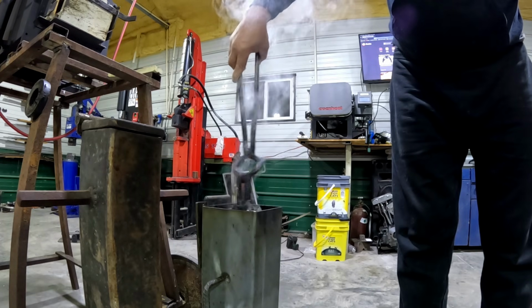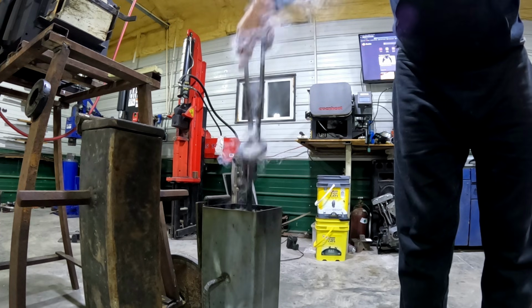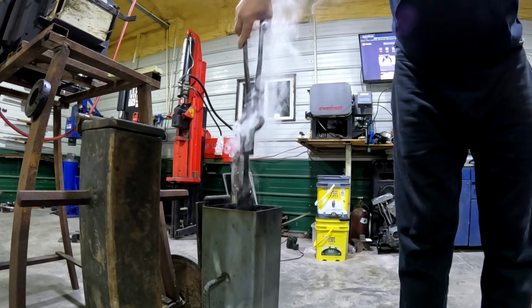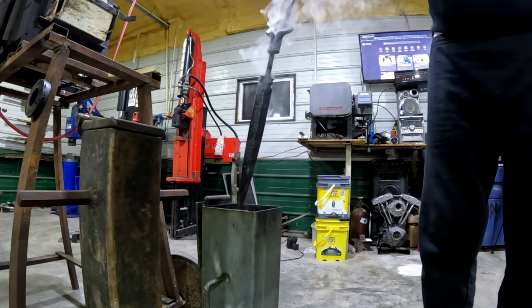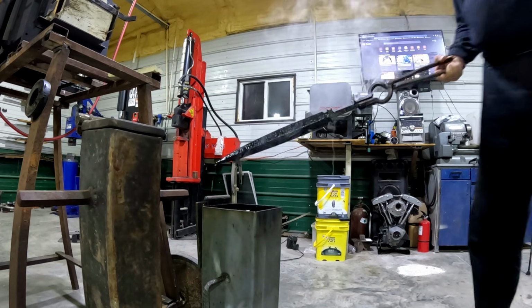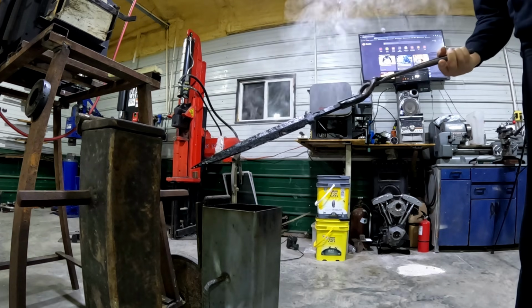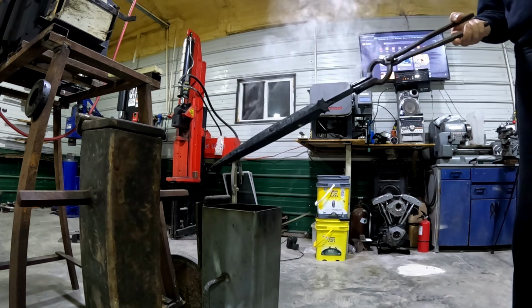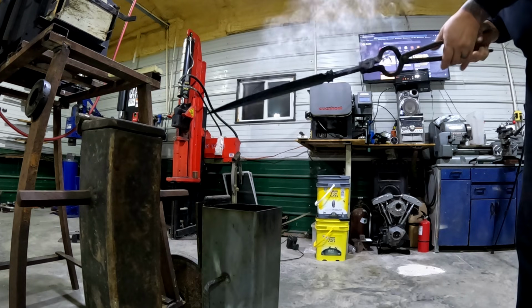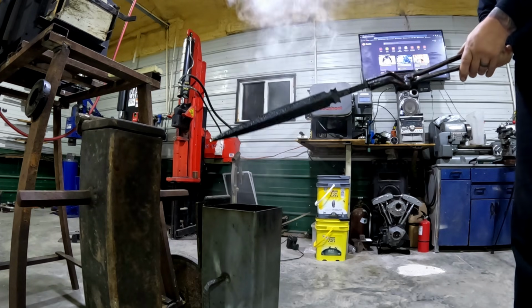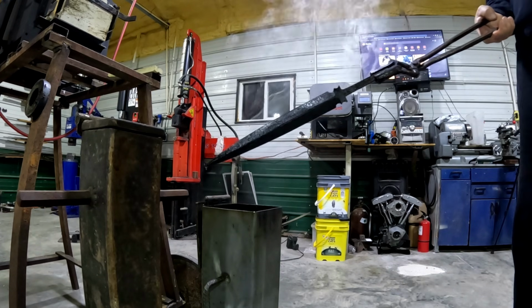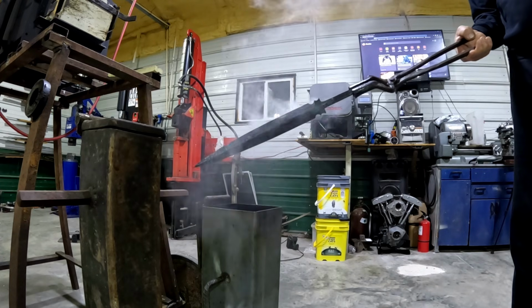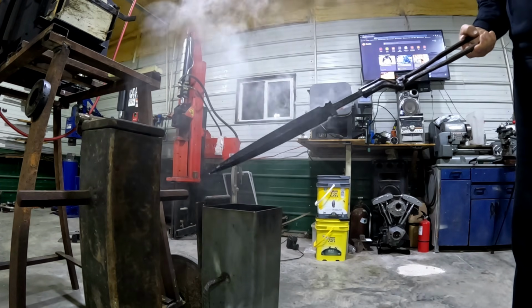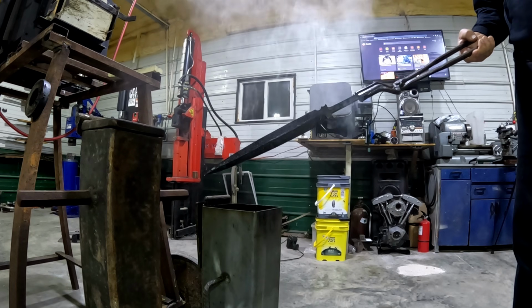I keep the dagger submerged until the oil's barely hissing. Just a lazy wisp of smoke when I finally lift it. That's the sign. Steel's down below 300 degrees Fahrenheit. Transformation's locked. Hardness is maxed. Pull it then, and a file just skates across like it's Teflon coated. Ting, ting, ting. Music to my ears. Perfect quench. No drama, no fire show. Just science, patience, and a blade hard enough to make a file cry.